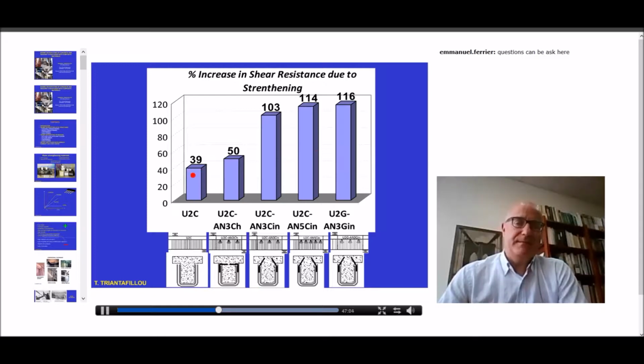For example, what is this? In this case, we have a 39%. In this case, the shear resistance increases by nearly 40%, 39%, in comparison with the control specimen. By adding, for example, 2 layers of carbon fibers, we can increase the capacity by nearly 40%. By using a U-shaped jacket, a 3-sided jacket, if we anchor the same jacket using those spike anchors placed horizontally in the web, that increases 50%.